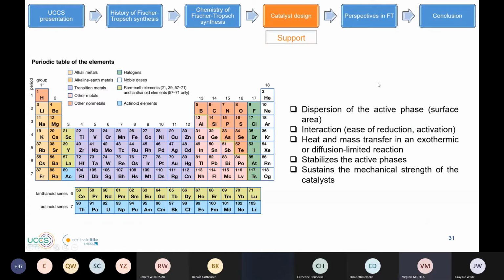So for support, in a supported catalyst, the support material usually represents the main component of the catalyst. So it is necessary to take into account the catalyst stability from the point of view of the active phase, and the support has the same importance. What we expect from the support is a good dispersion of the active phase. If we have a high surface area support, it will lead to better dispersion of the active phase. We need also interaction between the active phase and the support to avoid, for example, sintering. We need a support that allows heat and mass transfer in an exothermic or diffusion limited reaction. The support should stabilize the active phase and sustain the mechanical strength of the catalyst.